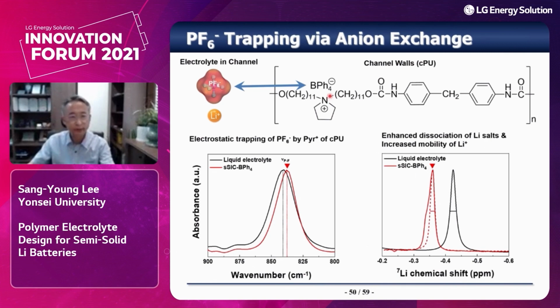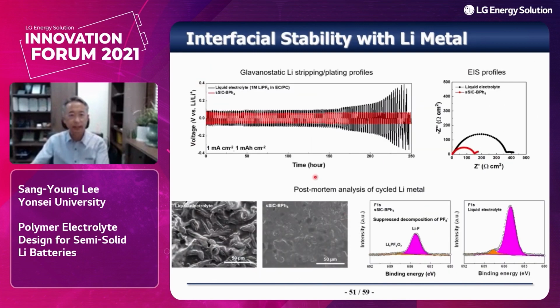Okay, and then we have focused on the BPh4 anion, which is the bulkiest one among the anion groups. And this is the evidence to demonstrate the anion exchange. The PF6 minus was replaced, captured by the cationic groups, and from the NMR result, enhanced dissociation and increased mobility was achieved. Okay, and then as you can expect, the single ion conducting electrolyte shows stable plating and stripping behavior, and this is confirmed by the post-mortem analysis.